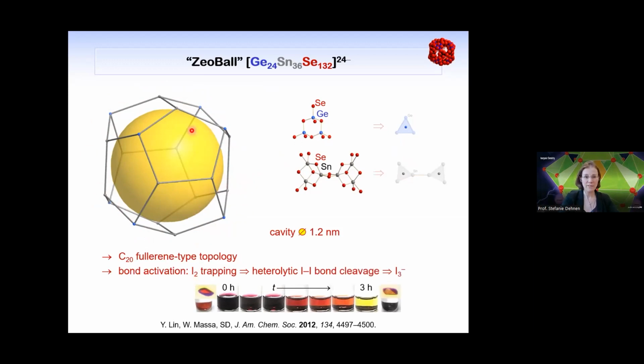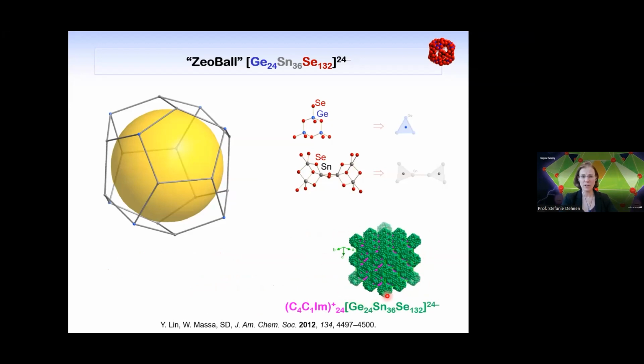We can also use this cavity for doing chemistry, like in some kind of a nano flask, which is shown here. You take the red crystals and soak them in a solution of iodine in cyclohexane. And over a time span of 3 hours, you will see a fading of this solution, and the color turns brown. You see this better here. And what we have found is that we form triiodide. So we have a heterolytic iodine bond cleavage and form triiodide this way, which tells us that this is a pretty reactive compound.